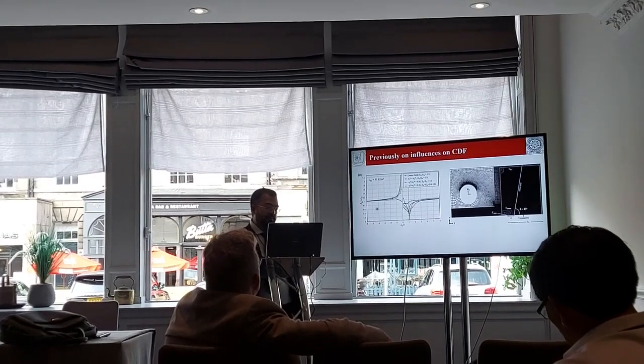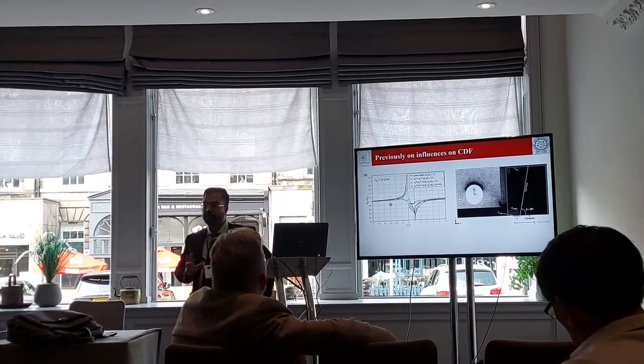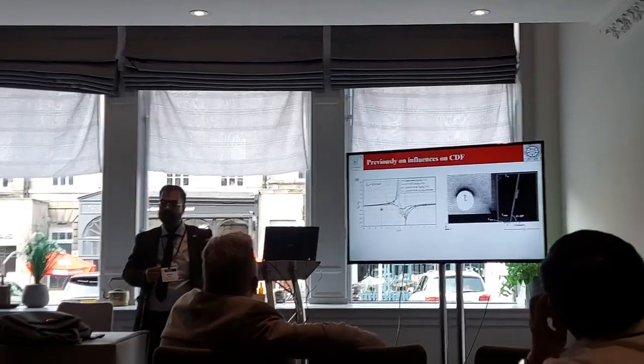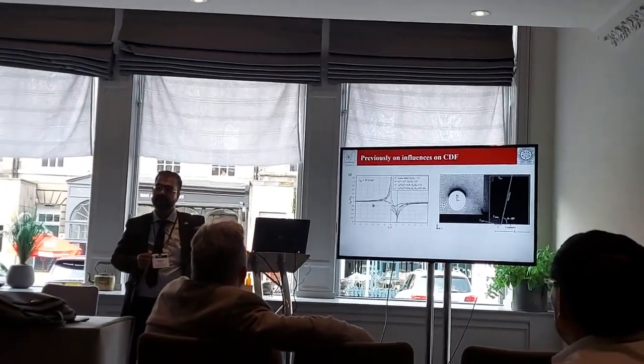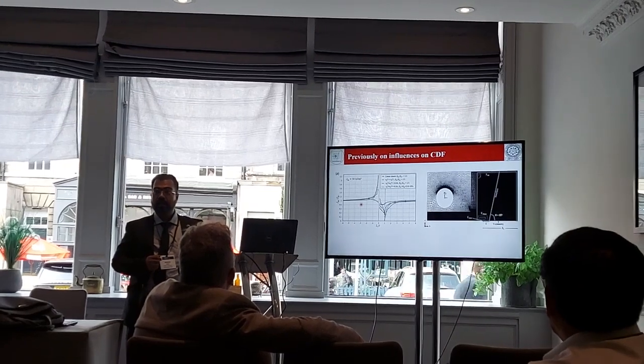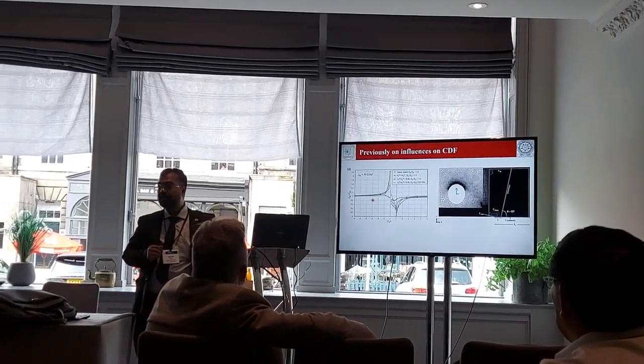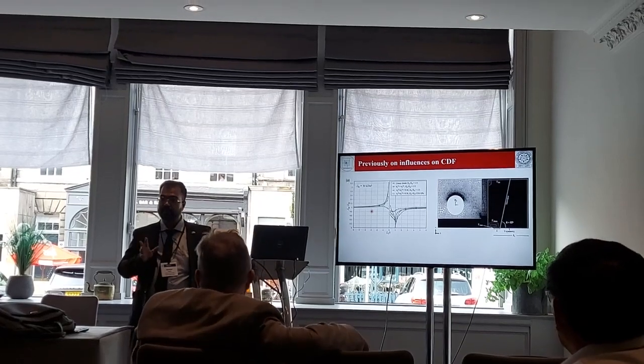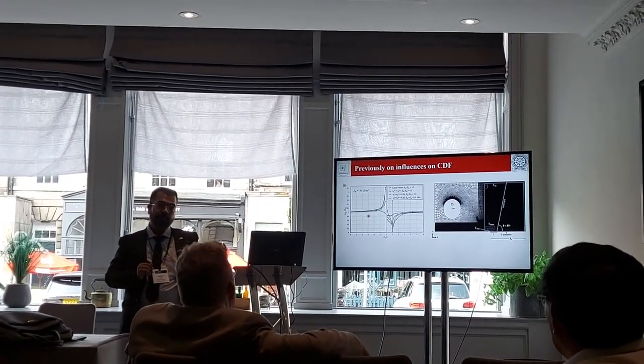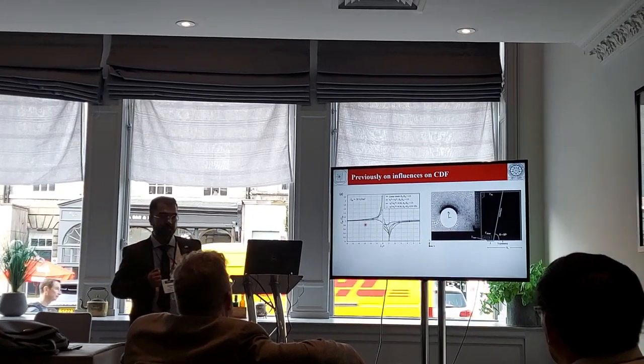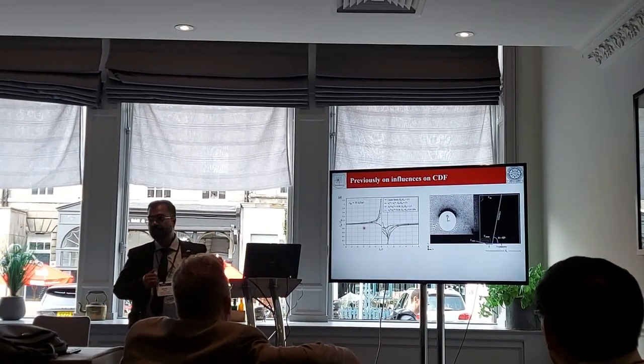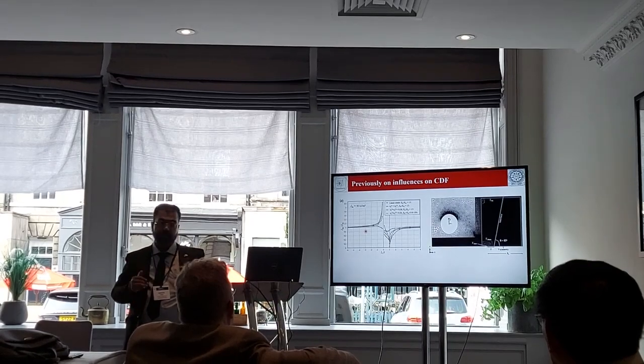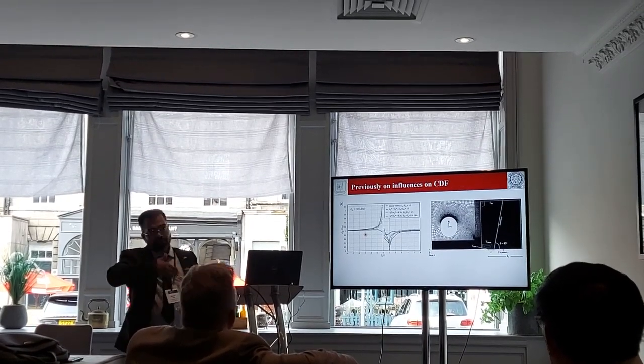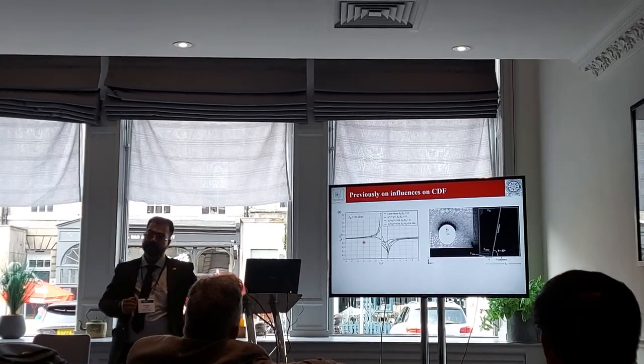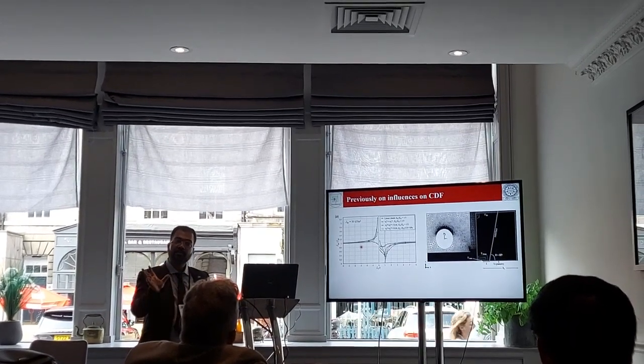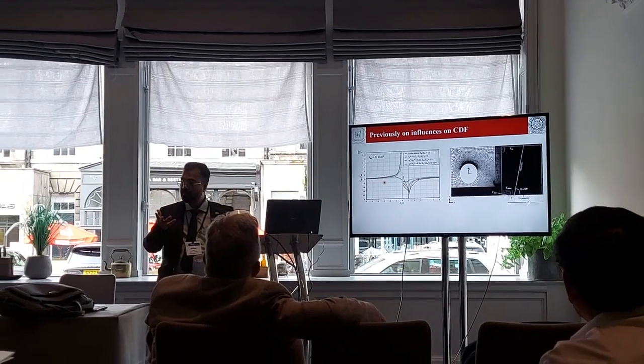In this graph, what you see is the normalized crack driving force, or the pseudo elastic energy release rate in terms of J integral from Rice. We calculate it via a different route, which is by the application of configurational forces, which I will try to explain in a bit. On the y-axis, you have the normalized crack driving force, and on the x-axis, you have the normalized distance from the interface. The blue dotted vertical lines represent the interlayer. This interlayer is different from the matrix material, so it can be a weld zone, for instance.